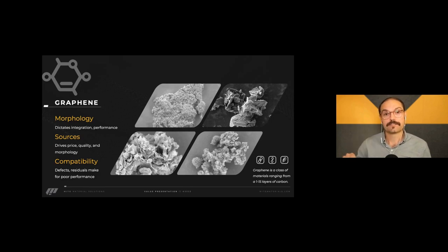On this slide, all of these materials are considered graphene, but you'll notice they are very different in structure. The top right is considered graphene itself, but when you look at it under SEM or XRD — common characterizing methods — you see it's more along the lines of graphite. Morphology and structure really plays into how you choose graphene. If you have a flat structure, it's harder to integrate but can increase electrical, thermal conductivity and mechanical properties. A more ball-like structure produces the opposite.